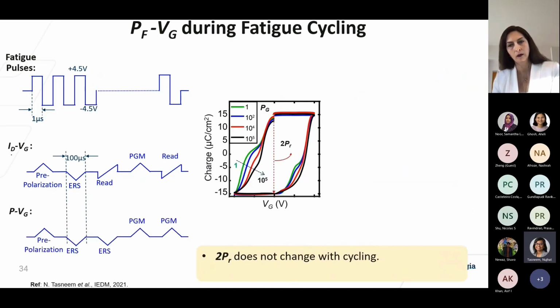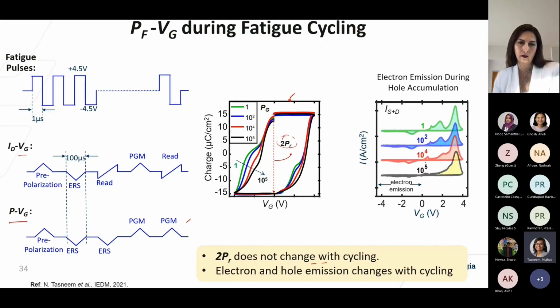Along with the ID-VG characteristics, we also applied the split-pulse technique on this FFET at each cycling decade. So this is the result of the split-pulse technique, which we get by integrating the switching currents. The results show that the 2Pr value, or the remnant polarization of the FFET's gate capacitor, does not change with cycling. What ends up changing is actually the amount of electron emission, shown by these peaks at the negative voltage side of this figure during hole accumulation, and also the hole emission during electron inversion. So again, bottom line is that 2Pr does not change with cycling, but the amount of electron and hole emission are the values which end up changing with fatigue cycling.